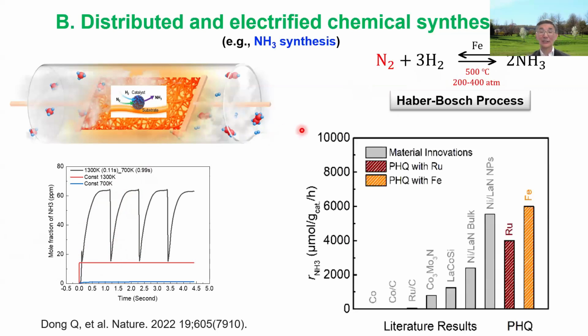In the laboratory, this is the experiment we collaborated on. You can see the ammonia yield per micromole per gram of catalyst powder for the different catalysts. There was an ammonia workshop in China recently, and Professor Hosono of Japan showed that Ni/LaN nanoparticles can have the highest yield of ammonia. By shifting equilibrium, even with a simple iron catalyst, we can have equal or even better performance than Ni/LaN. This is another indication that manipulating non-equilibrium can enhance the yield and selectivity of critical e-fuels and chemicals.